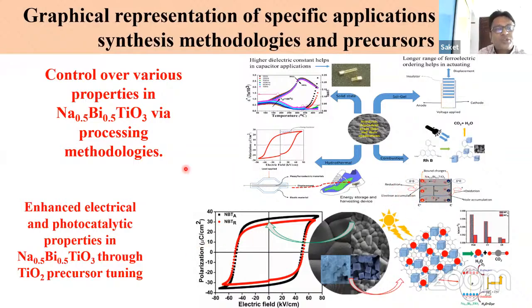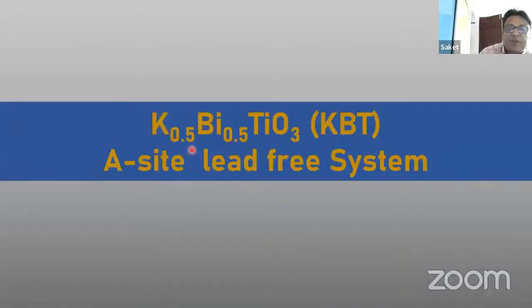Of course, when you make this material, we have to use starting materials, for example sodium carbonate, bismuth carbonate, or TiO2. TiO2 has two different types of precursor with different structures: one is anatase, another is rutile. Even if you change that precursor, it varies things, which we have observed in the photocatalytic activities. In case of rutile versus anatase, the reaction rate is better in case of anatase if you synthesize with that. So that is the role of the precursor, you can say.